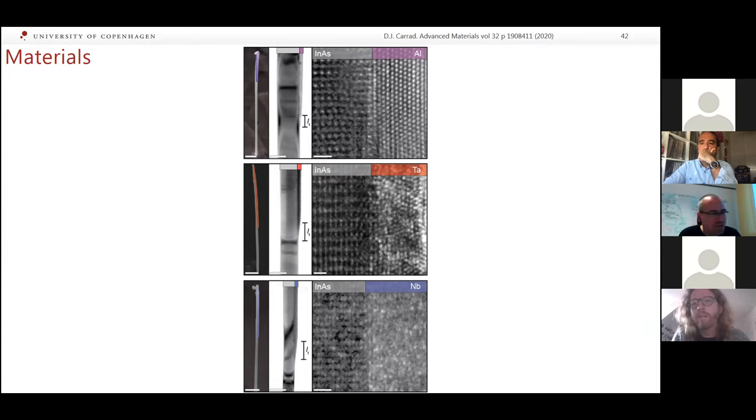Okay, thank you, Damon. Maybe just very quickly before we move on, I see no further questions from the audience. I saw that the induced gap from tantalum is less than the induced gap from aluminum. Is this understood? Yeah, so the induced gap of aluminum depends on thickness, of course, and it does for tantalum as well, and actually for many other superconductors. But for aluminium, if it gets thinner, the gap gets bigger. Tantalum goes the other way. If it gets thinner, the gap gets smaller.